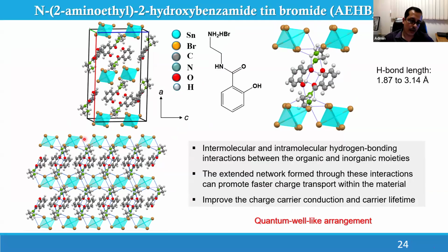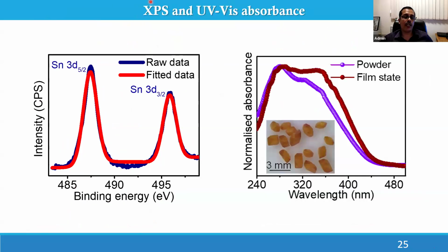It has isolated octahedral structures, but these are connected well through hydrogen bonding and through the organic component. You can see the OH, C double bond O, NH, NH2. All these are capable of forming hydrogen bonding, and because of that, we were getting a very robust structure, and we confirmed it is a Sn4+ structure, not Sn2+. Sn2+ normally oxidizes easily to Sn4+ and decomposes the perovskite structure. So we were not willing to work with Sn2+. We worked with Sn4+, and this is the absorption in the powder and in the film state.